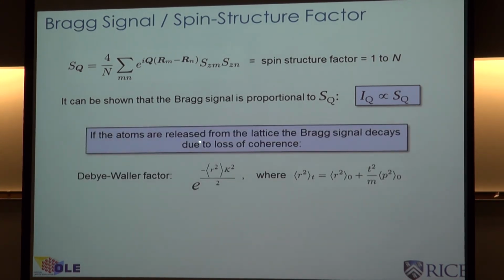So the atoms give us this constructive scattering only if they're very well localized on a lattice site. And if the lattice is weak, then there can be some uncertainty in the atom's position on the site, and that weakens a little bit the coherent signal, and that's called the Debye-Waller factor. It's the same thing as the Lamb-Dicke parameter. For those of you who, I know there's some ion trappers in the audience somewhere. And so this is exactly the Lamb-Dicke parameter. It's exactly the same thing. That's R squared, K squared. And in this context, it's called the Debye-Waller factor.